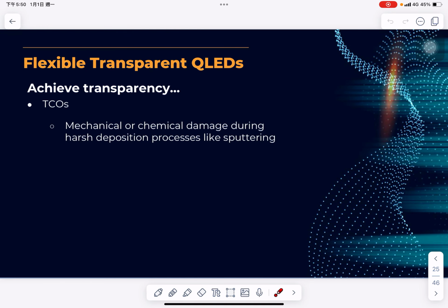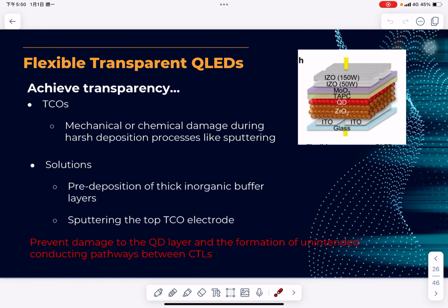TCOs are common transparent electrodes, yet crafting a see-through top electrode using TCOs is challenging due to potential damage from harsh deposition methods. Strategies involving pre-deposition of thick inorganic buffer layers followed by sputtering the top TCO electrode have been implemented to prevent damage to the quantum dot layer and the formation of unintended conducting pathways between charge transport layers. The structure is like this.